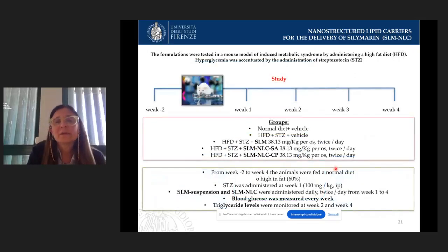To discriminate the best formulation for delivering silymarin extract, we performed in this case an in vivo test. In this case, the formulations were tested in a mouse model of induced metabolic syndrome. The metabolic syndrome was induced by administering a high-fat diet, and also we induced type 2 diabetes in the mouse, and then hyperglycemia by using streptozotocin. From the literature, silymarin has good results in reducing the blood glucose levels and also the triglyceride levels. Then we administered to the mouse silymarin alone and also our two formulations.